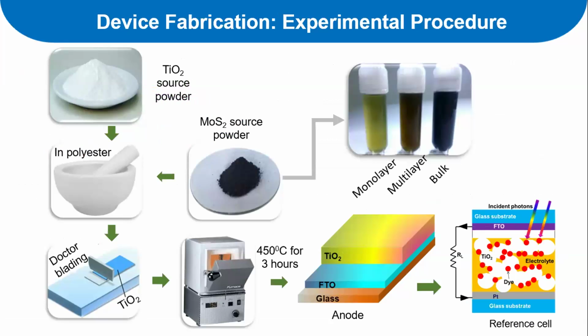So this is a very simple device fabrication procedure to obtain an excitonic photovoltaic device. We have an electron acceptor. In this particular case, I just discussed titanium dioxide as a source material, which can be mixed with polyester, and then we can make a colloidal paste. Once we have the colloidal paste, that can be screen printed or doctor-bladed on top of a transparent conductor, which has already been coated on a substrate. Most of the time this is glass, and then we go for an annealing process. This is a 450-degree annealing process for 3 hours.